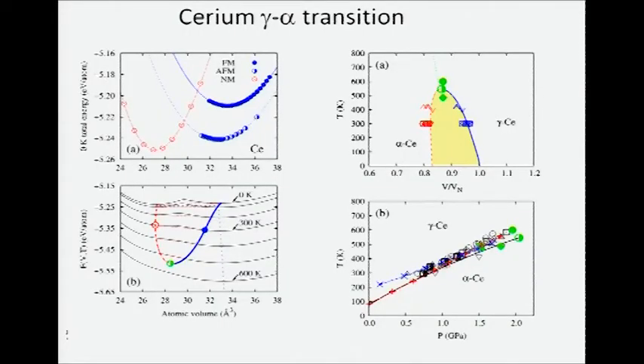But we first did a simple calculation. We treat cerium - because of strong correlation, we tried one non-magnetic configuration, tried one ferromagnetic configuration, and tried the anti-ferromagnetic configuration. Using that formulation, you can derive the free energy curve. At low temperature, it shows a double well, which is called a miscibility gap. Then with increasing temperature, due to that configurational entropy, the double well disappears.